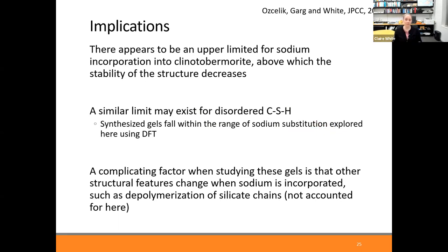And this is still to be proven, because what we're doing here is using a model crystalline structure to infer what is likely occurring in the disordered gel. But without looking at the disordered gel directly, we can only infer, we can't prove that it's the case. And so, for example, there could be ways of using, say, force field molecular dynamics simulations to explore the same question, but looking also at the impact of disorder on the system, so that you're more representative of what we know these gels to be like in real life.